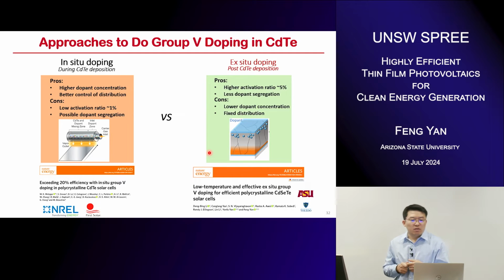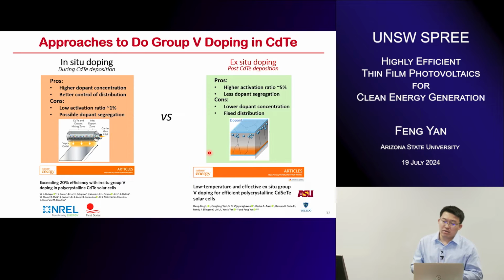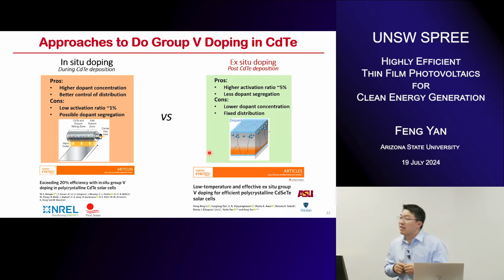So almost 4 or 5 years ago, I collaborated with Dr. Feng Yan at the University of Toledo, trying to see if we can borrow the same concept as copper doping from the back surface. We call it ex situ doping or diffusion doping. Initially, it was very challenging because the group 5 dopant is difficult to introduce. Compared to copper going to the cadmium site, it's pretty challenging to drive the group 5 dopants into the tellurium site using the diffusion approach. But we succeeded with this technique, with efficiency of roughly 18% previously, but we are trying to further engineer it.